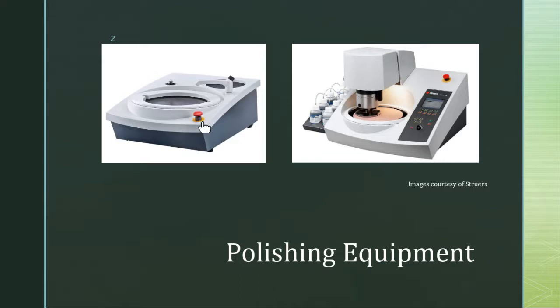As a metallographer, you will get agitated if you do not have patience. It's better to take 30 seconds to clean in between steps instead of spending a whole day trying to fix a sample. Remember, sample prep is important, especially if you're trying to hit a specific target. You can't grind through your entire sample and say, oops, I lost my sample now. So cleanliness is number one.